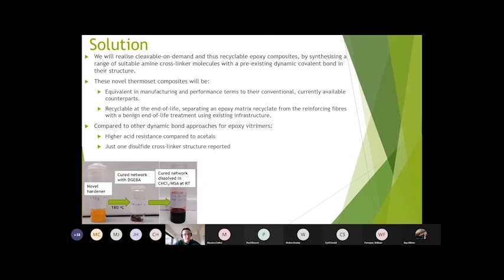You can see our little proof of concept on the left-hand side there in the images. In the vial with the yellow powder is our novel epoxy hardener. That is, in essence, an aromatic amine that we have synthesized, and that's why it is being cured at a rather high temperature of 180 degrees.